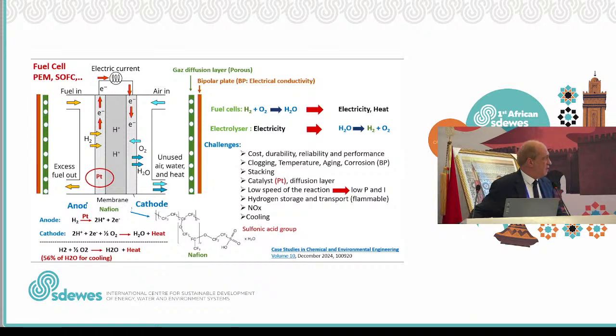They are very expensive. They have problems of durability, of reliability, and of performance. They undergo some problems of clogging, because you have many products that clog the membranes, and you have problem of aging, corrosion of bipolar plates, and the stacking. What they have shown here is just one module. If you want to make a fuel cell, you have to bring different modules and you stack them. You stack them. And when you stack, you have problems, mechanical problems and electrical problems at the interfaces. And this is a huge problem. So we have to look for alternatives.